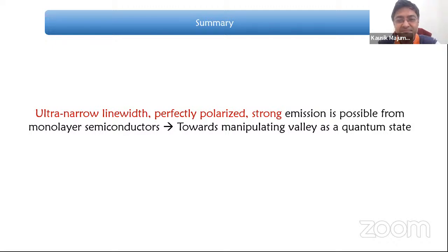I want two comments from you. One of them is that for achieving this 100% valley polarization, what can be the role of these vacancy mediated states and also interlayer excitons? So first I wanted to know, if there is a vacancy mediated state, like for some of these TMDC samples, we have seen that mid-gap states are extremely well localized, like a straight line. So if those can be utilized as trapping states, then definitely the exciton lifetime can be increased. But does it have any impact on valley polarization? So that is my first question.